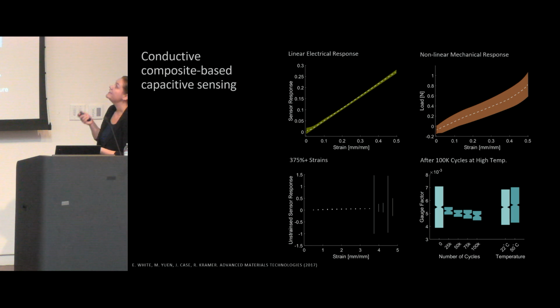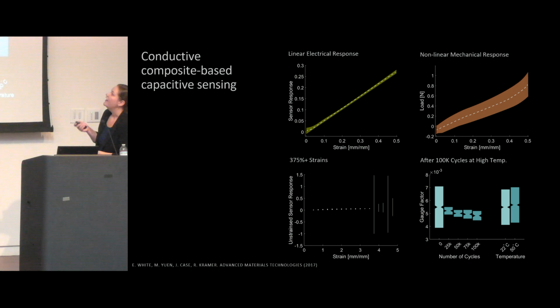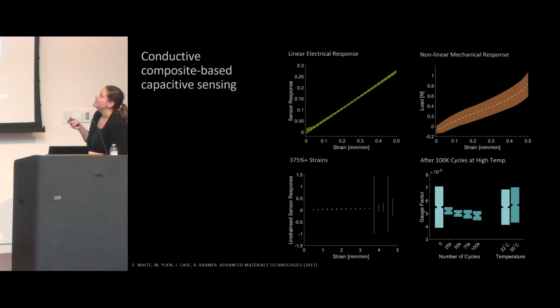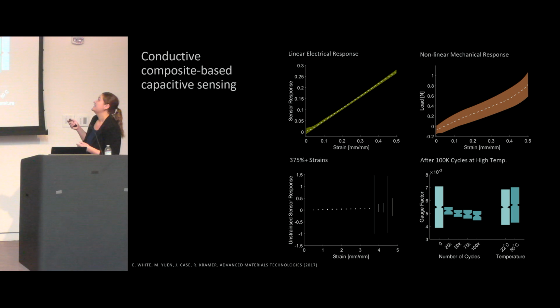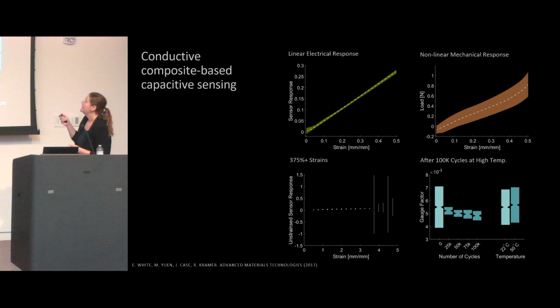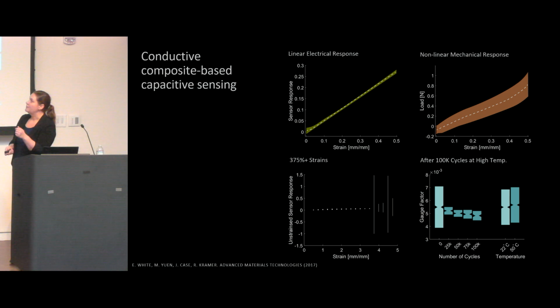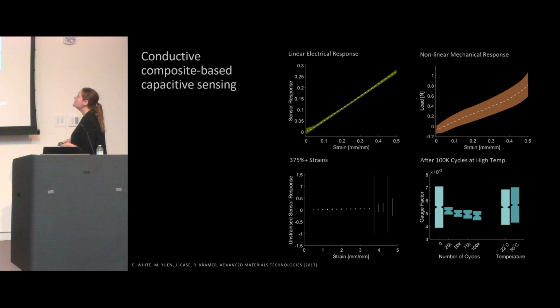So we have a nice linear response. This is one of the benefits of capacitive sensing and stretchable capacitive sensing. Our capacitance response to strain is typically very linear. We have an expected nonlinear mechanical response to strain. It's a fully elastomer layup, so that's highly expected. This particular sensor operates up until about 375% strain, sometimes higher. So we think it's very accommodating to the types of soft robots and types of strains that we would be experiencing.